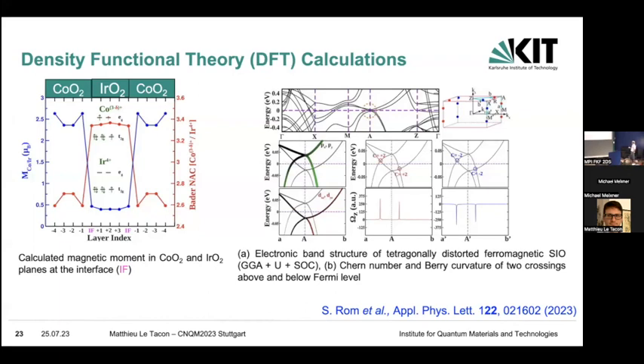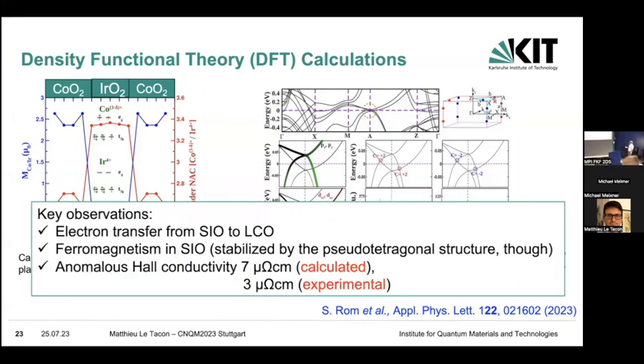But the reason why they found that this was magnetic is because when you strain the compound, you drive two degenerate Weyl points below the Fermi level. So you actually have two Weyl points with different chirality that are driven below the Fermi level. And so when you look at the Berry curvature and integrate it, they estimate that this should give rise to an anomalous Hall effect of 7 microohm centimeter, which is about twice what we observe experimentally. So this is in quite good agreement.